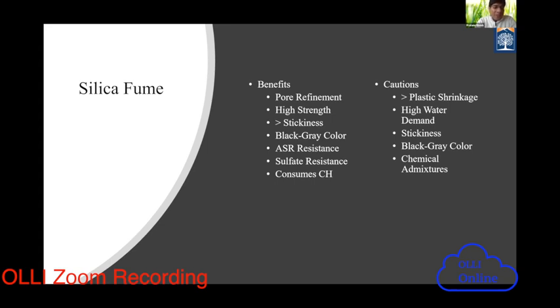In some situations, like fast track paving, the contractor mentions that we need to pave it out in next 7 days basically, and we need to have the very good strength. So what we do basically, that time we need to have a concrete that can generate the strength which is generally going to be reached by 28 days. So we provide silica fume definitely, so that we can generate the very high strength within 7 days comparable to 28 days strength, and the fast tracking can be easily done.